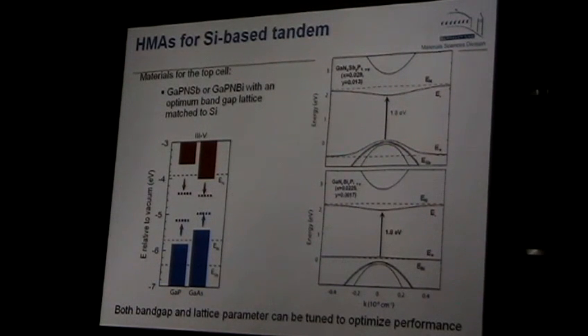There are obviously some issues here, that these are alloys. Alloys in general have properties which are inferior to compound semiconductors and non-alloy semiconductors. And as you saw, for example, mobility is very strongly affected. Mobility in gallium arsenide and antimonide went down drastically, cold mobility. So these are the issues of transport in these materials. However, as long as we have large absorption coefficients, so we can absorb in very thin films, then it is probably still acceptable for some applications.